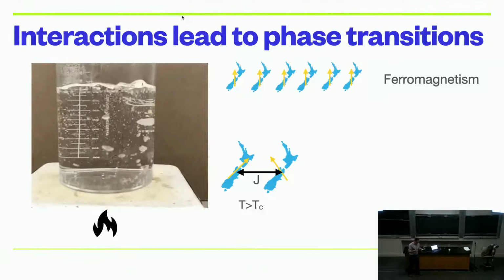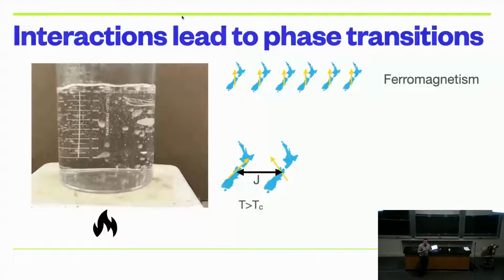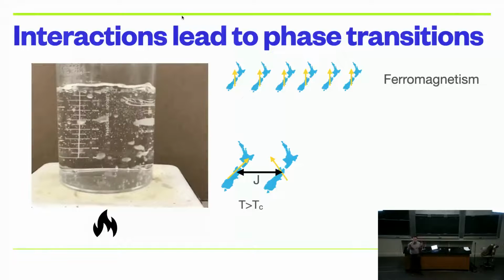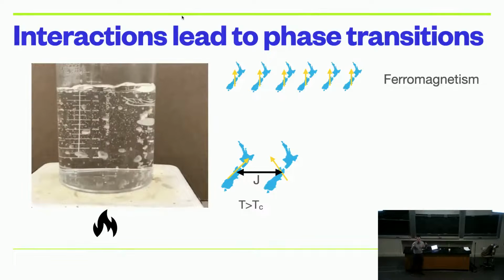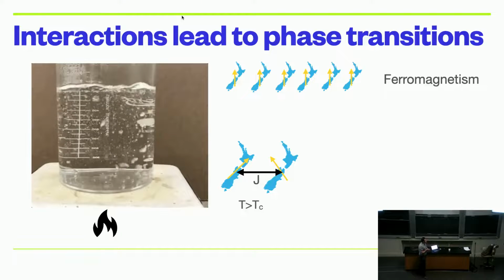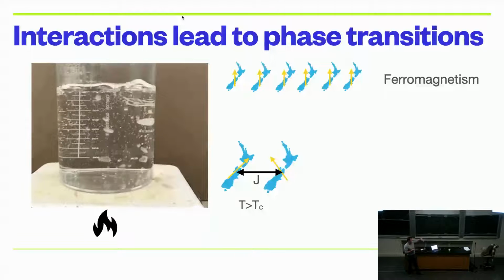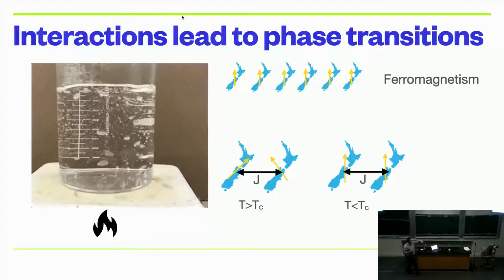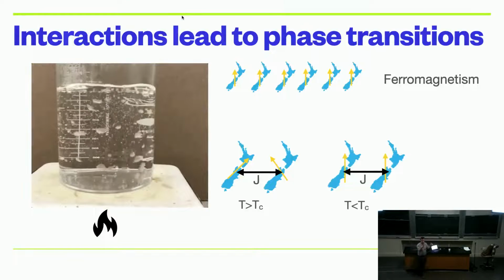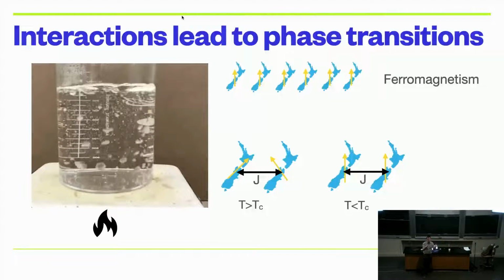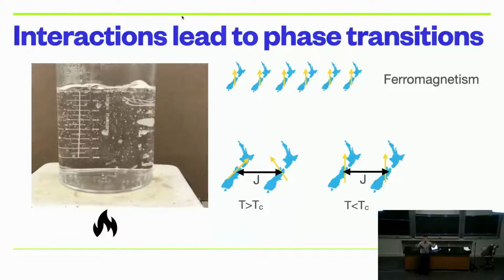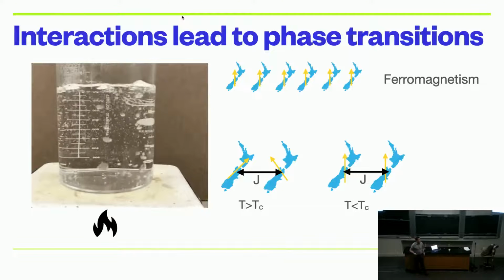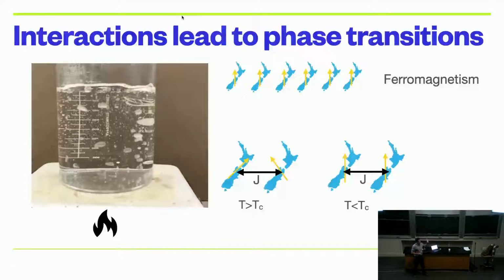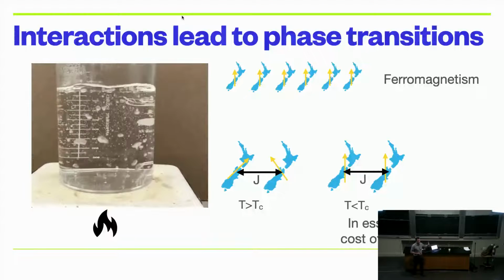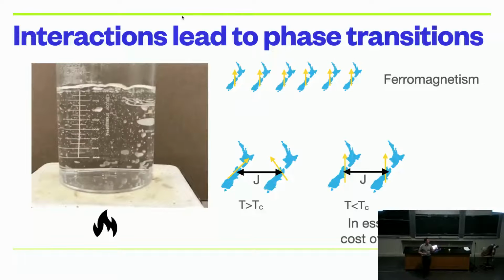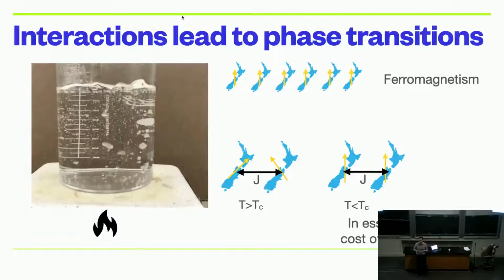At high enough temperatures, if the temperature has an energy scale that's higher than that interaction, those spins can just freely move around according to what we call thermal fluctuations. But as soon as the temperature drops below that energy scale with which they talk to each other, then they start to see each other on some time scale and some length scale. And now they start to move in harmony, and eventually all of those spins line up together, and that's what we call a ferromagnet. The specific kind of interaction in this case is known as the exchange interaction, and in essence you can understand it as the cost in energy of exchanging spins between sites.